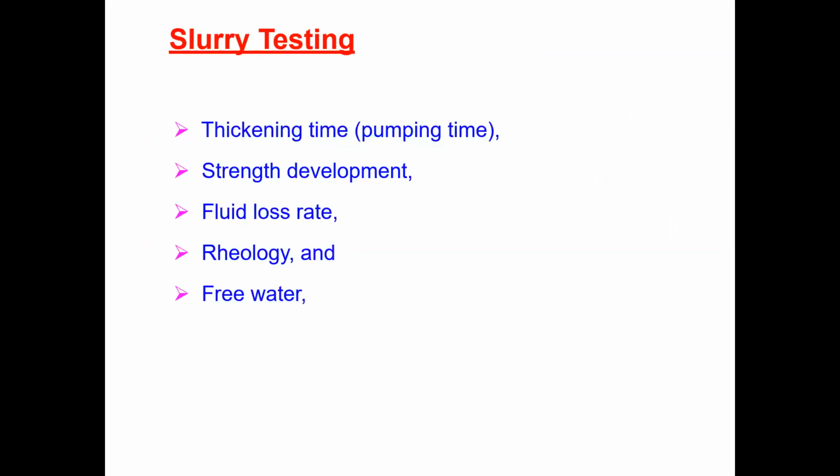Okay. So these are the tests: by using a consistometer, thickening time is measured. Then strength development: the ultrasonic cement analyzer, UCA, is available, which is non-destructive testing. Or otherwise, conventional cubes also we can make, and those cubes can be kept at curing temperature under bottom hole static conditions, and then we can carry out destructive testing. We can press-test them using a machine, and then we can know the compressive strength. And fluid loss rate is also measured. I have already told, the equipment is there. So 30-minute fluid loss is measured.